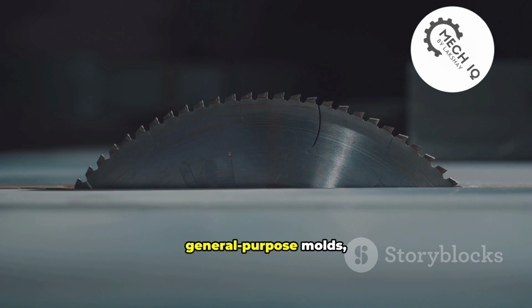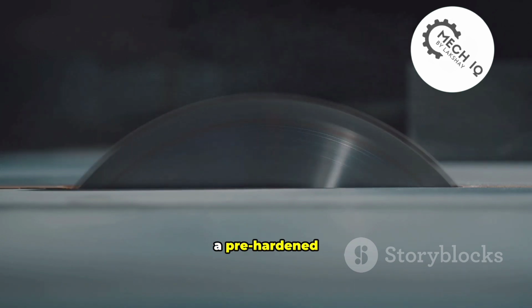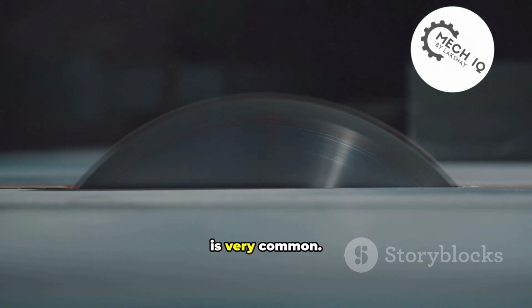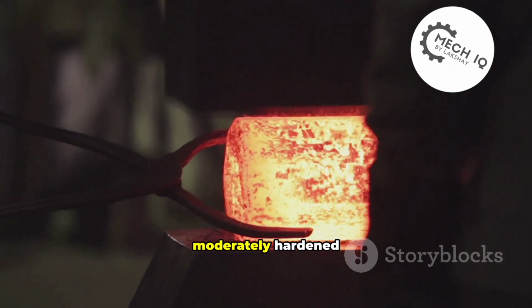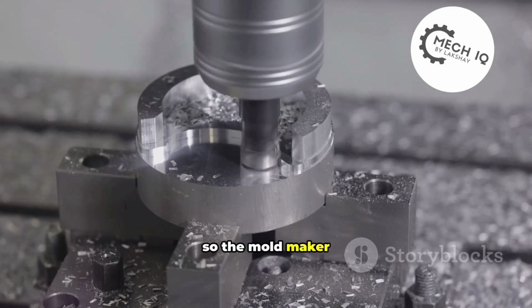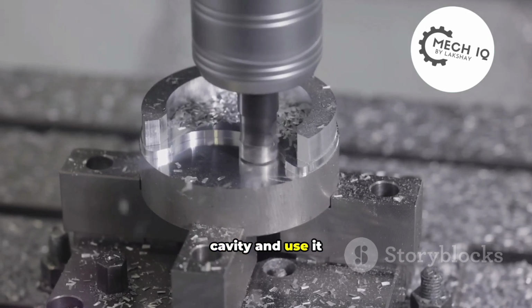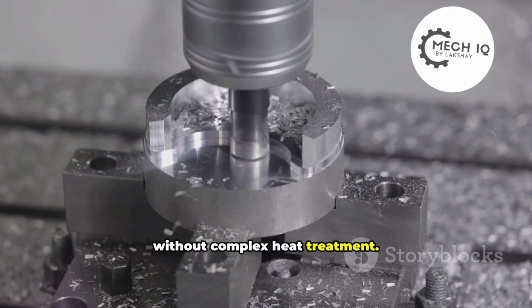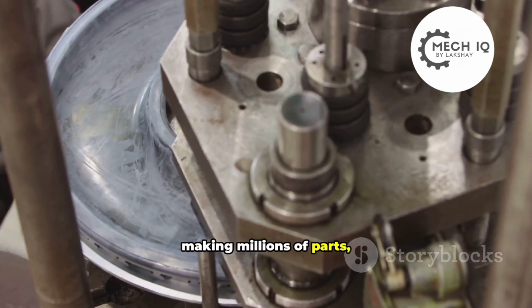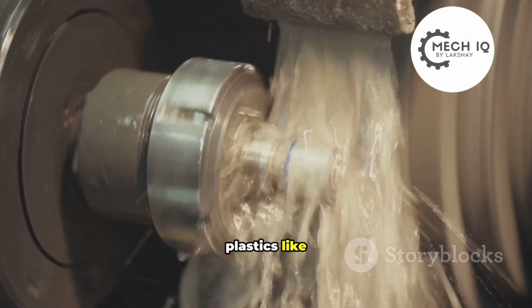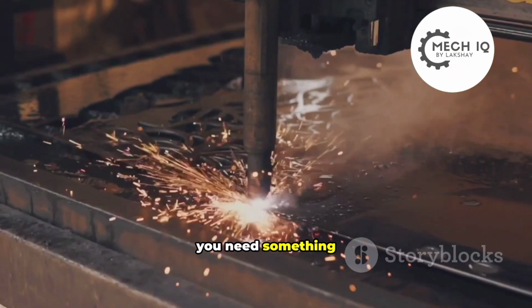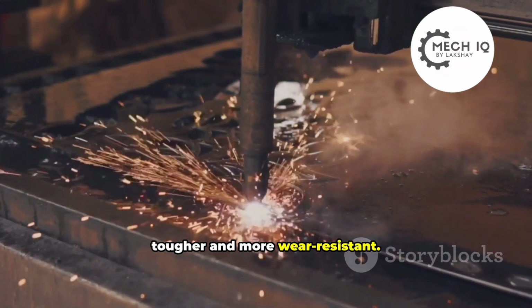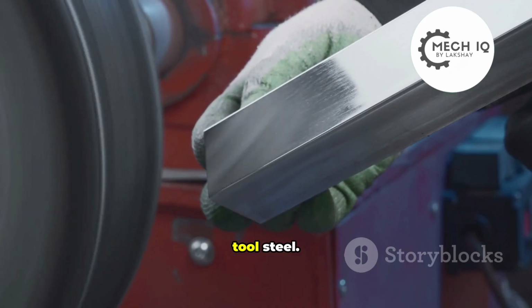For many general-purpose molds, a pre-hardened steel like P20 is very common. It arrives moderately hardened from the supplier, so the mold maker can machine the cavity and use it without complex heat treatment. But if you're making millions of parts, or using abrasive plastics like glass-filled nylon, you need something tougher and more wear-resistant. Enter H13 tool steel.